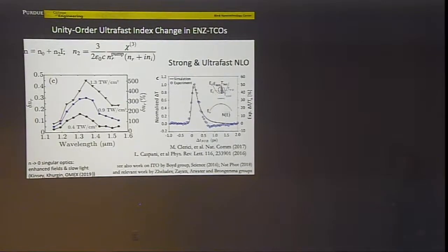And what is important is not only the huge nonlinear response, it's very fast. It happens on the scale of 100 femtoseconds. Because when it comes down to optics, as I like to say, the best electronics is called photonics, because optics is much faster than electronics. And so whatever you do with photonics, you should demonstrate the speed, because speed is what makes photonics advantageous when you compare it versus electronics. And here it's 100 femtoseconds.